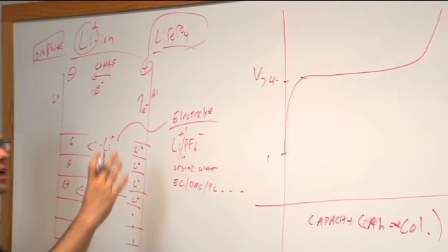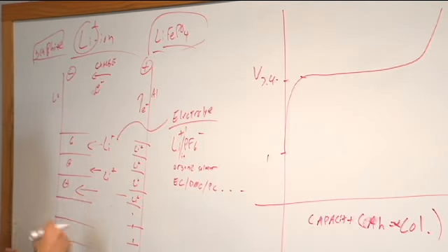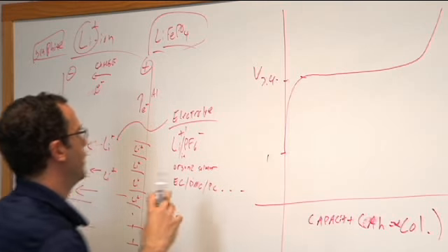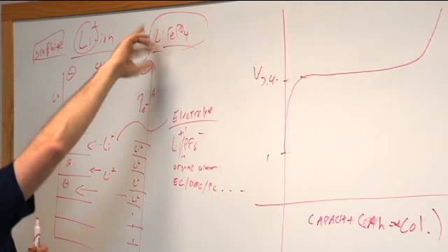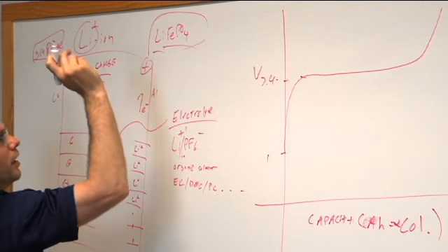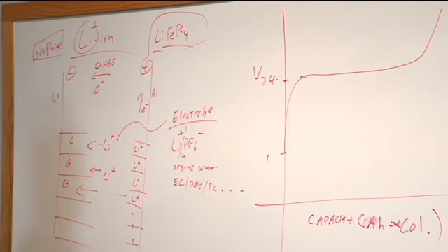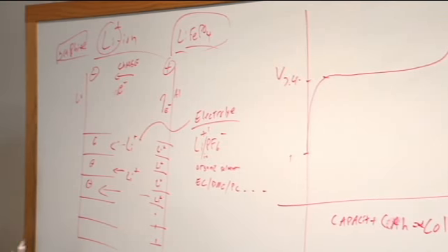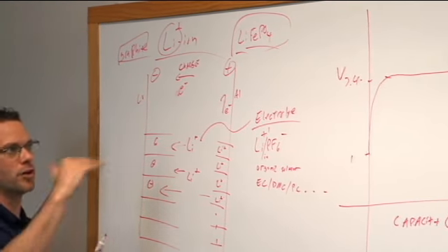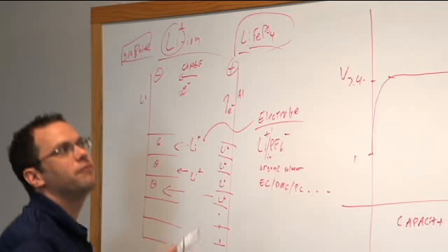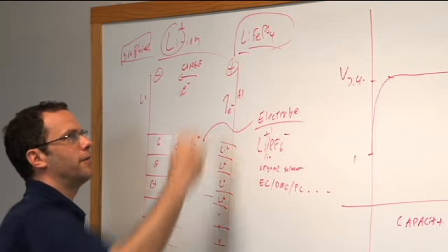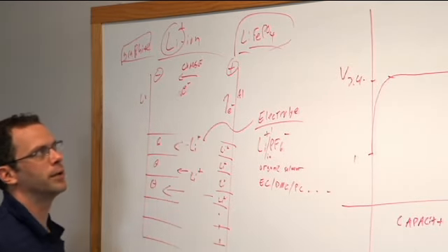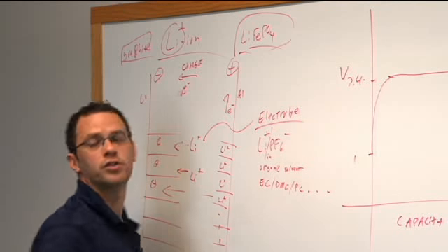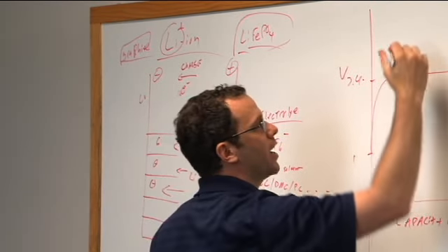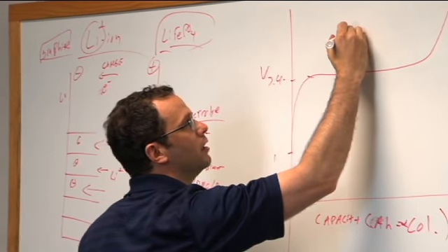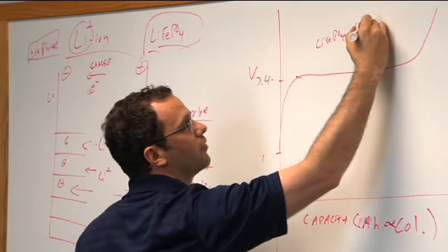And what's happening is as I'm going up, I extract this lithium out, and I reach this place where there's a phase change that occurs between lithium iron phosphate and iron phosphate. Just like when you boil water and change the phase between liquid water and gas, you have a constant temperature. We're doing a phase change here, going from lithium iron phosphate to iron phosphate. By virtue of thermodynamics and the Gibbs phase rule, we lock in the voltage at which it occurs. Okay? So in this range, we have a coexistence of lithium iron phosphate and iron phosphate.